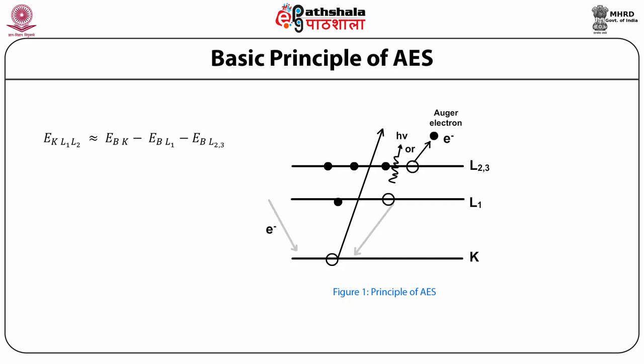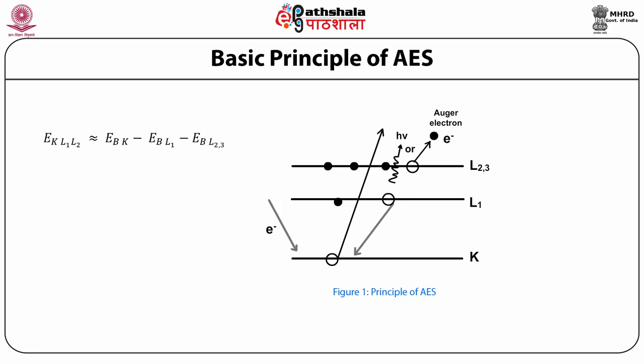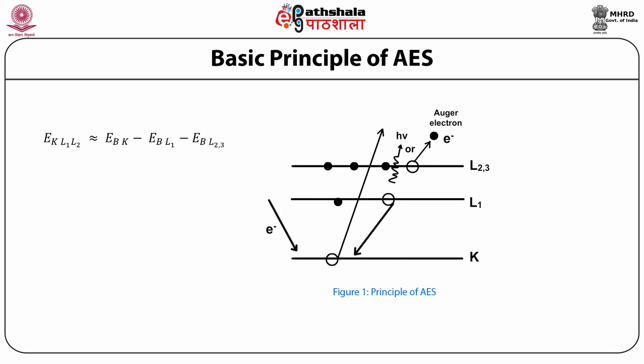The subscript of E_B X indicates the binding energy of electron shell X. For example, E_B K is the binding energy of the K shell. Auger electron spectroscopy identifies the elements by measuring the kinetic energies of the Auger electrons. In the spectrum, an individual kinetic energy peak from an Auger electron is marked with an elemental symbol and subscripts indicating the electron shells or subshells involved.